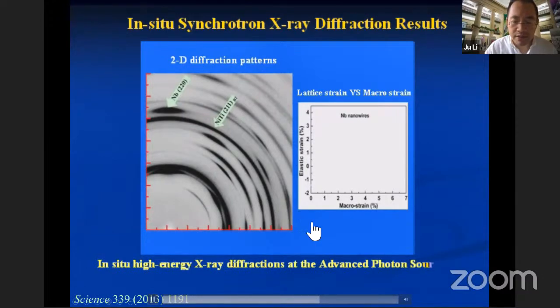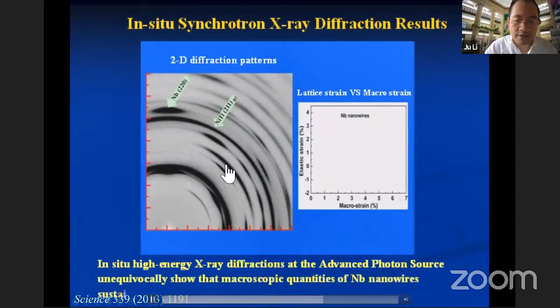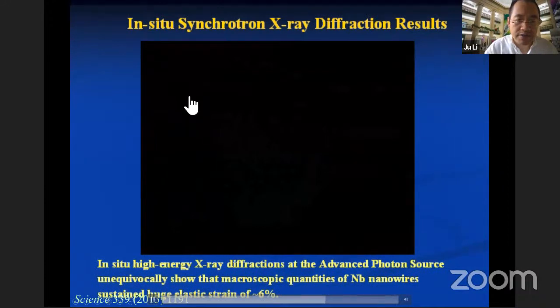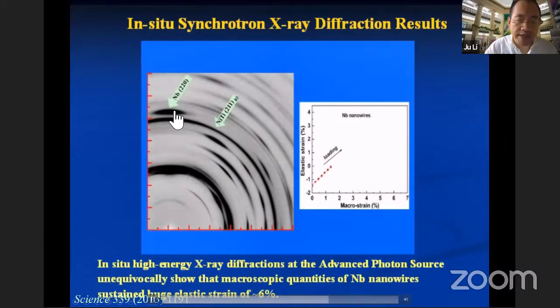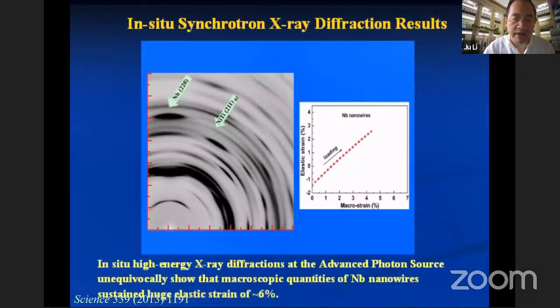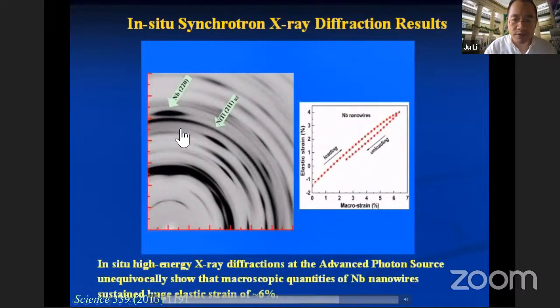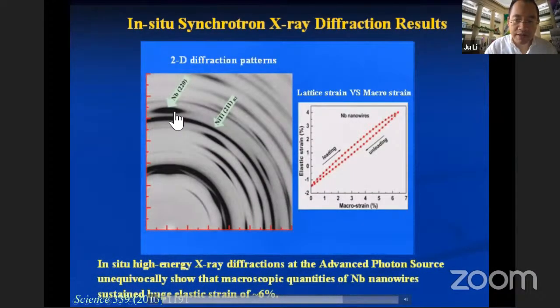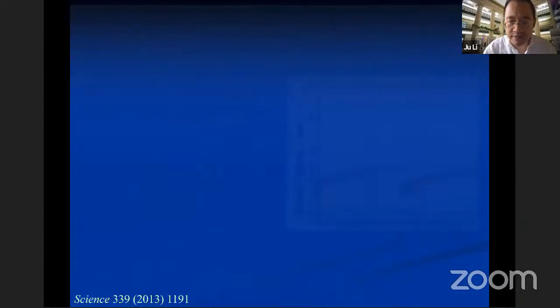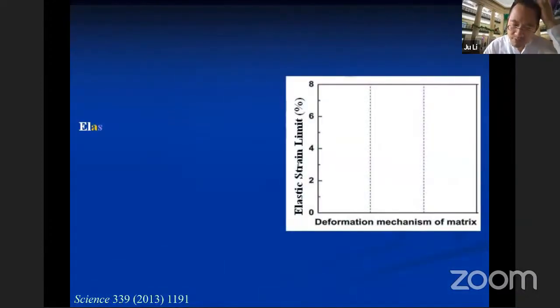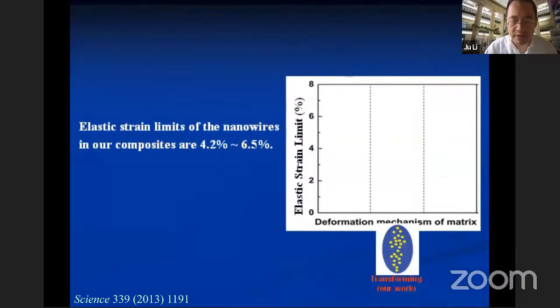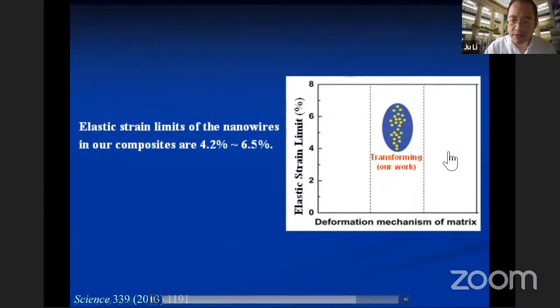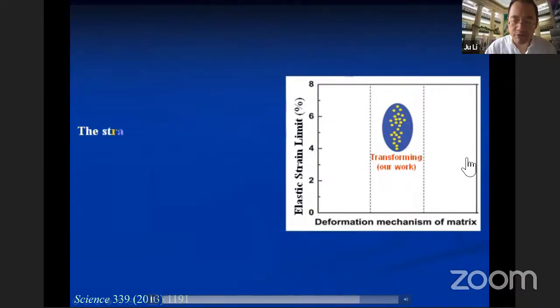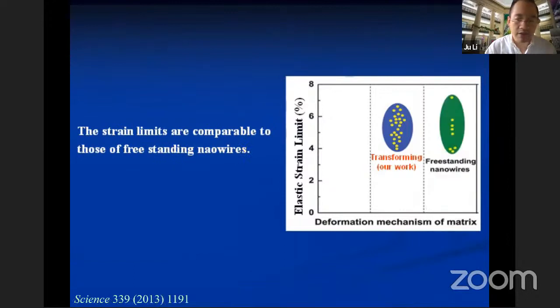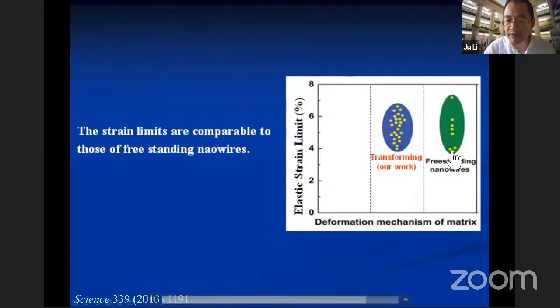We have done in situ synchrotron diffraction at the APS at Argonne. So this is the niobium 220 peak, and I've never seen this before in my career, that you see such a huge shift in the XRD peak. So this shows that the niobium is undergoing a true elastic deformation. And what is very important is that you must have a shape memory alloy matrix that's undergoing this B2 to B19 prime phase transformation.